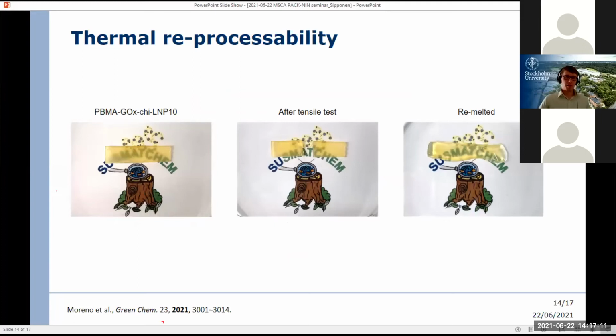And one more dimension to this is that we can of course be critical: is it a good idea to combine a synthetic plastic with renewable organic material? So how can this be reused or recycled? Well, we cannot give the full answer, but we at least can give a partial answer to this question. We studied that after we have broken this specimen with 10% of the lignin particles, it can actually be reprocessed by simply melting it again. And this could be more like a reprocessable material before the eventual disposal at the end of the lifetime.